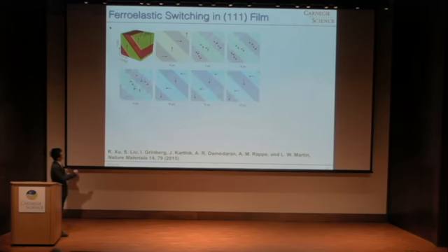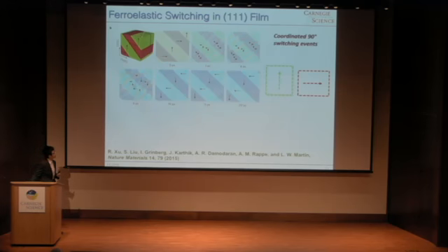If we compare the initial and the final domain pattern, we find that many dipoles undergo 180-degree switching through successive 90-degree switching. We know that 90-degree switching is ferroelastic. Then why can this kind of ferroelastic switching happen in a thin film, which is clamped by the substrate? I think this is because whenever there's a 90-degree switching chain from A to C, there's a compatible switching chain from C to A. Therefore, macroscopically, the elastic cost is not that big.